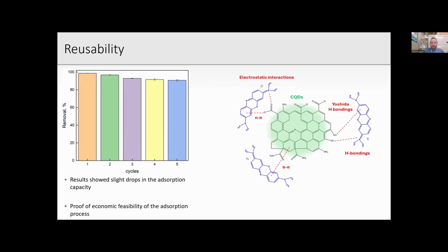Reusability tests, even in this case, proved that it is possible to use this membrane again by removing the cationic dye just by soaking the membrane in a water hydrochloric acid solution in order to remove the adsorbed dye. So this membrane can be used again, proving again the adsorption capacity of this membrane and justifying the economic feasibility of the adsorption process.